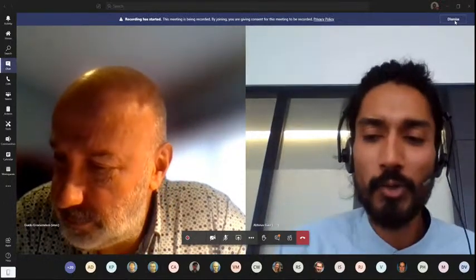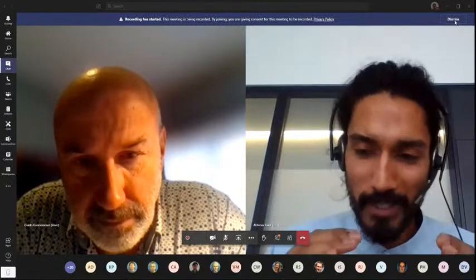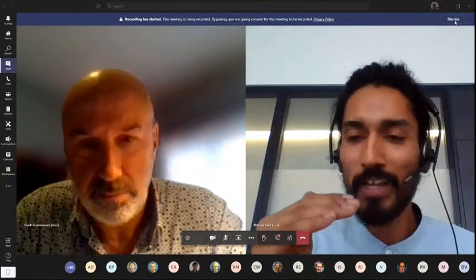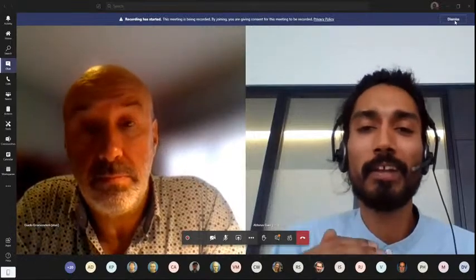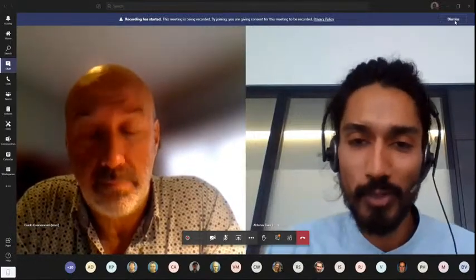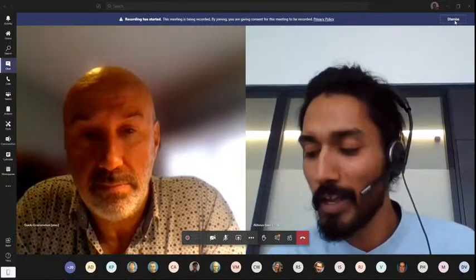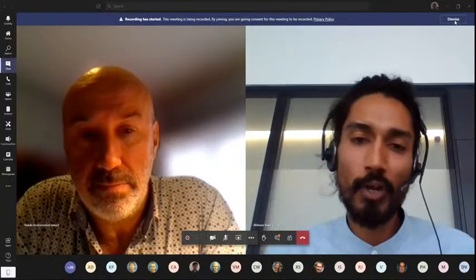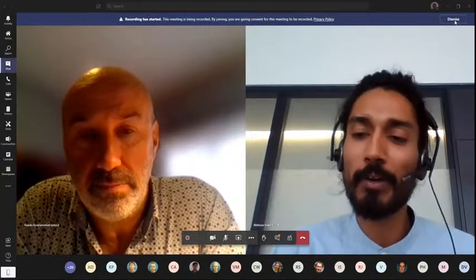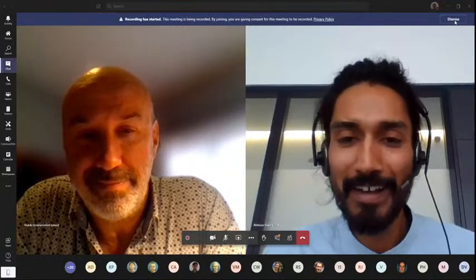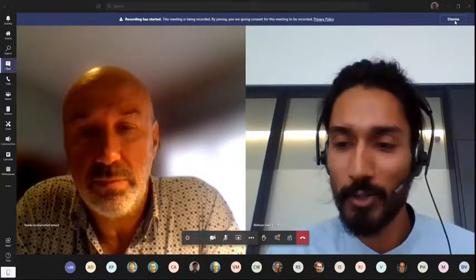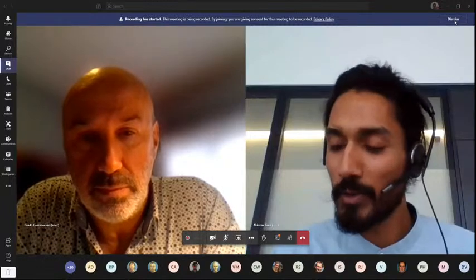So the reason for going to STO was just because we had found that this is a very high K, and this would be a very nice study to see how much higher capacitance we can get in MoS2. This was the main idea of using STO, right? Most of our work was focused on hafnium oxide because that's the most relevant oxide currently, if you think about silicon processing as well, right? So good high K, and it's well understood.